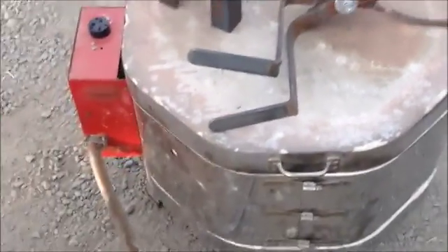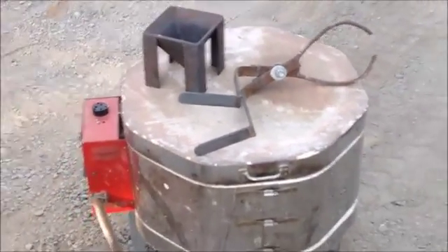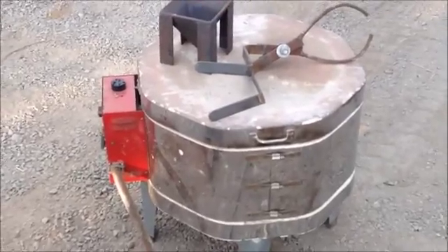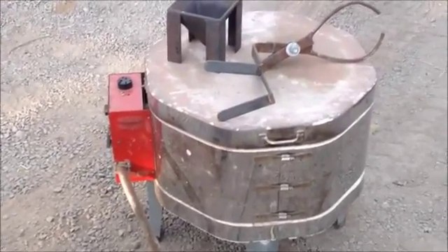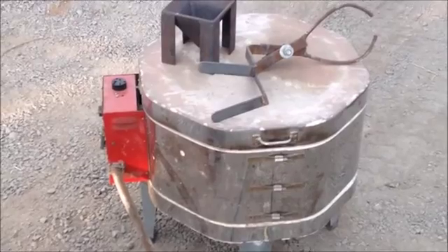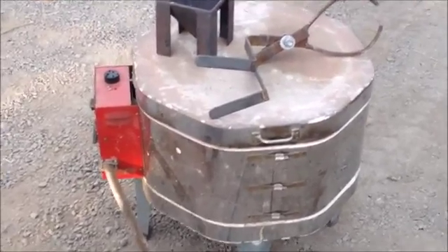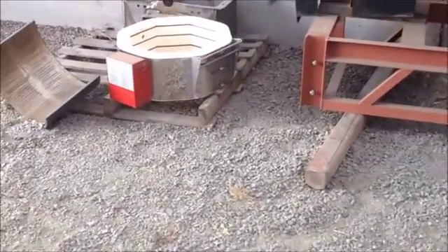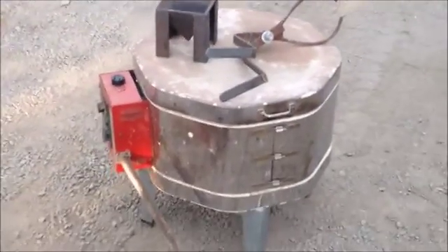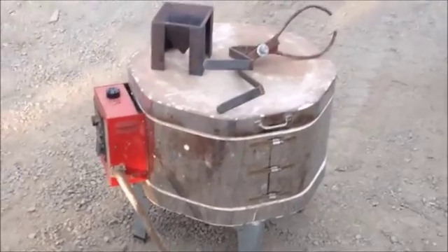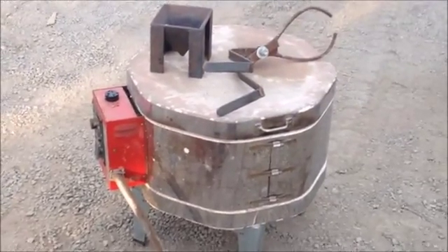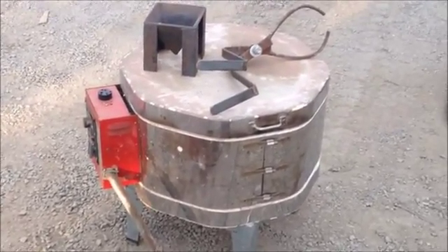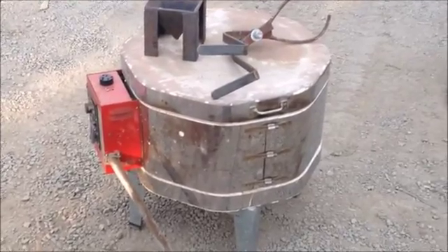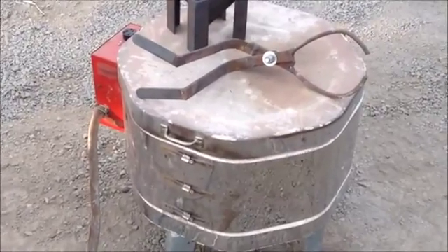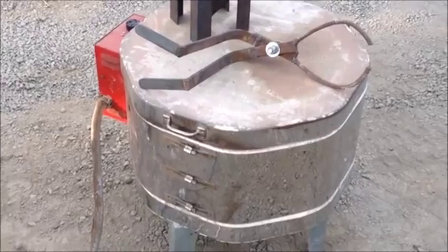And like I said earlier, this is really a kind of an R&D experimental project. I got the kiln for a couple different reasons. One, it was fairly cheap, but also you can put a really pretty good sized crucible. It's actually sitting over there. I have another segment that can go on top of there, so I can actually probably put about a number 80 or 100 crucible in there, and so I can do a really big smelt once I get the hang of it in an oven that's real cheap. I probably have less than $500 in this whole thing, including crucibles and flux.